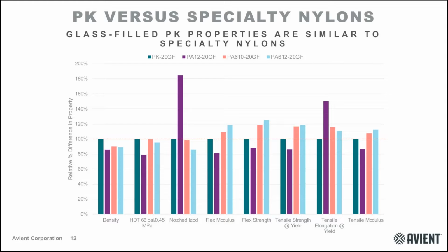And what you really notice in this graph is a lot of the properties seem to match that bar near 100%. There is a little bit of a difference for the glass-filled nylon 12 for impact rating, but broadly, there are good similarities and good agreements between all of these samples. And so the take-home message here is that polyketone can be a solution, a replacement for applications that are well suited to specialty nylons, especially when you consider the advantages in sustainability and cost in use.